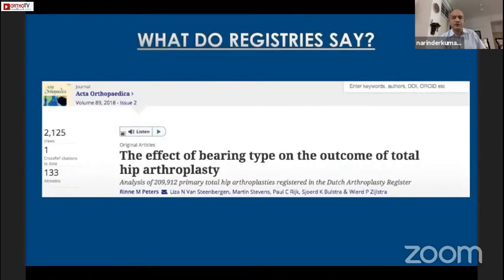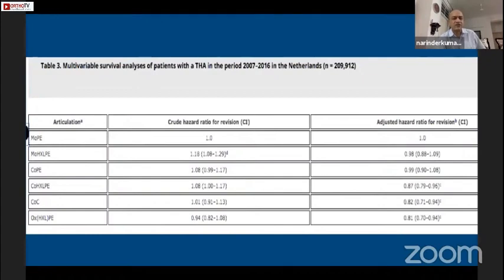So with all these options which are available commercially to us, let's see what the registries say. The Dutch Arthroplasty Register published in 2018. I was actually surprised. I was expecting that the revision rates would be minimum for either ceramic on ceramic or ceramic on cross-link poly. I was surprised to see actually the Oxinium on cross-link poly has the least revision rates. And of course, ceramic on ceramic was one above it. And as expected, metal on conventional poly had the highest revision rate.